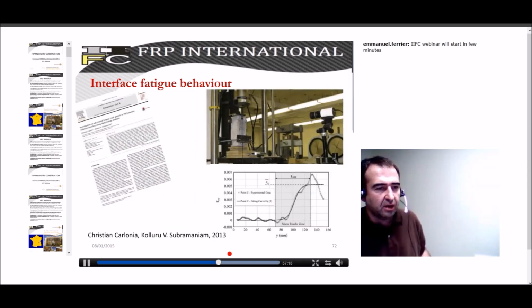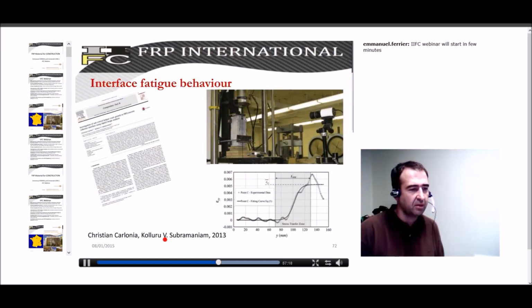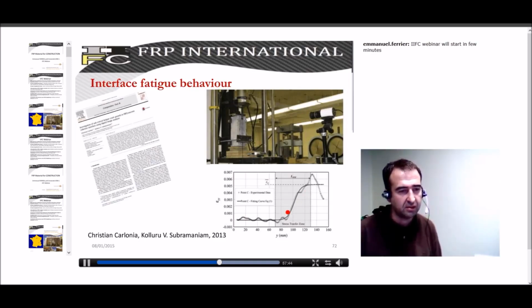Other tests done this time by Christian Carlonia. This is an interesting paper because it observed the fatigue process with a non-destructive, full field image analysis, allowing to get the strain along the bond length. And you can observe here that the bond length again is very short, less than 100 millimeters, and they have observed this all during the fatigue issue. So this study is also very interesting if you are interested in the fatigue behavior of the adhesive.